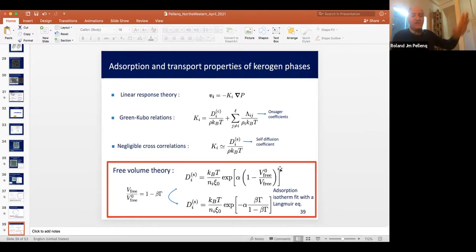It's the amount of surface area every molecule covers per second where the mass center of the fluid doesn't move. But the transport coefficient is where you have a transport, the mass center of the whole fluid is moving through the porous material. But in those conditions of nanopores, we can see that the self coefficient equals the transport coefficient. So basically, we can relate an equilibrium quantity to an out of equilibrium quantity.